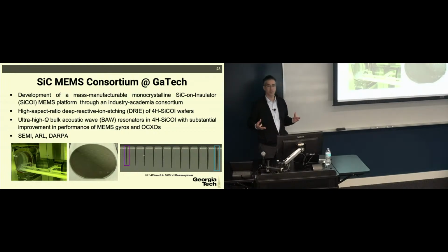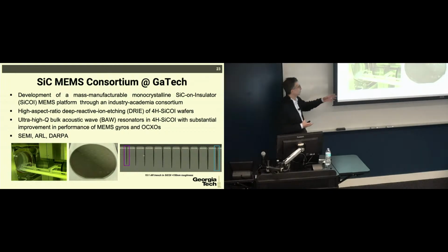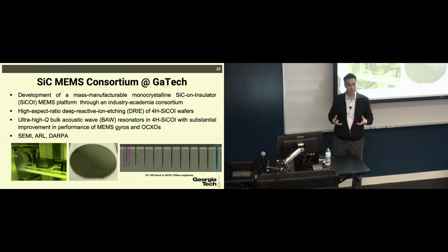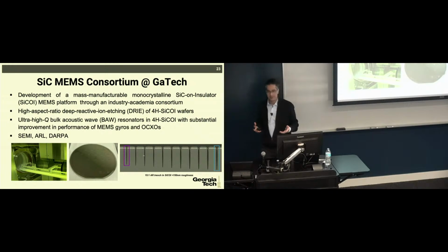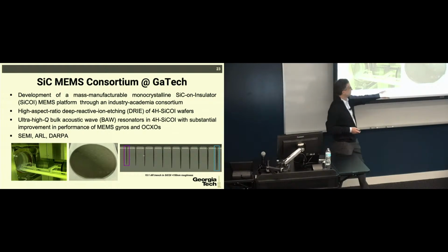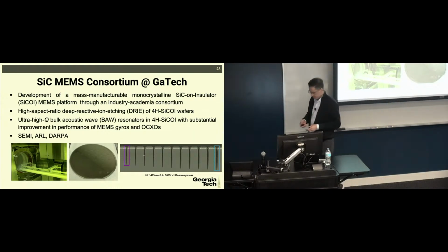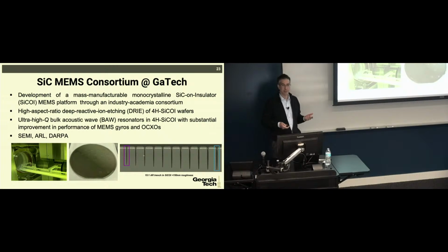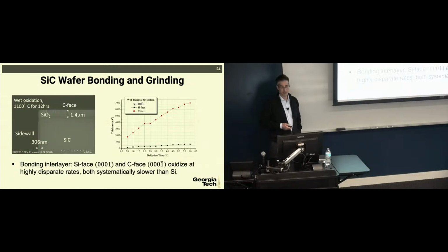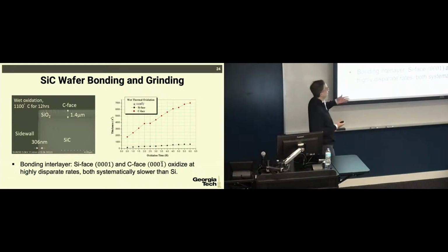They are still much more expensive than silicon. One of these 6-inch wafers would be about $1,200 compared to $50 you pay for a silicon wafer. So this silicon carbide on insulator wafer that you see here, after it's all processed, is going to be about 3x more expensive than a silicon on insulator wafer after processing. And then there are certain things that you have to be careful about with silicon carbide. For example, it has a silicon face and a carbon face. The silicon face has a much lower oxidation compared to the carbon face.